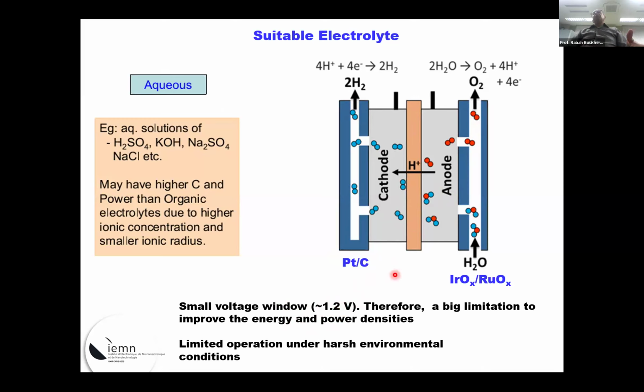Although often I wouldn't say this is really the case, because most of the electrode materials, specifically if you use the transition metals, you extend this voltage window, because most of them don't exactly behave. Works mostly for noble metals. So if you use transition metals, this will open up 1.5 to up to 1.6 before you can start having either oxygen evolution or hydrogen evolution. Nevertheless, when you work in water, indeed, you have certainly a limitation related to this water splitting.